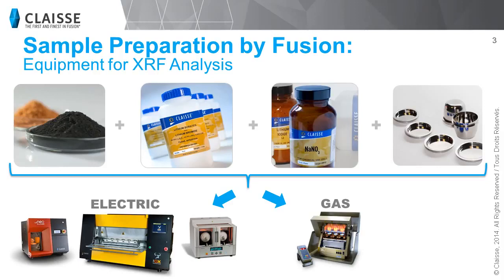An automated fusion instrument should be used in order to ensure safety and higher productivity. This instrument can be heated by gas or electricity. At Claisse, we offer resistance heating fusion instruments such as the Neo, which can prepare one sample at a time, the Eagon 2, which can be used to prepare two samples at a time, and the TheOx fusion instrument, which can prepare up to 6 samples at a time for higher productivity. We also offer the M4 fusion instrument, which is heated by gas, liquid petroleum, or natural gas. It can prepare 3 samples at a time.